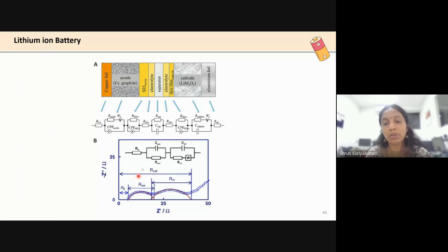So you know that this is what is happening. Majority you have bulk electrolyte resistance, all of it probably coming from the electrolyte contribution, because your metal current collectors are not going to contribute much. And then whichever is your SEI component, that is going to give you an SEI resistance. And then you have your charge transfer Faradaic component associated to it. So this is how you are going to get your Nyquist plot.